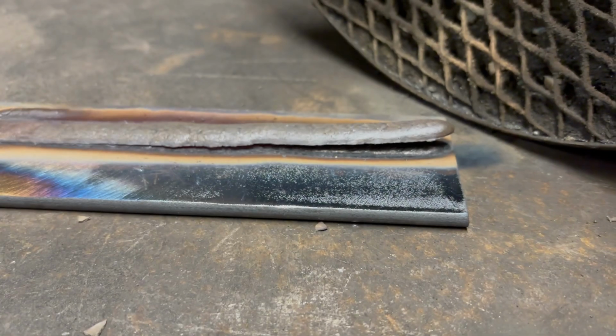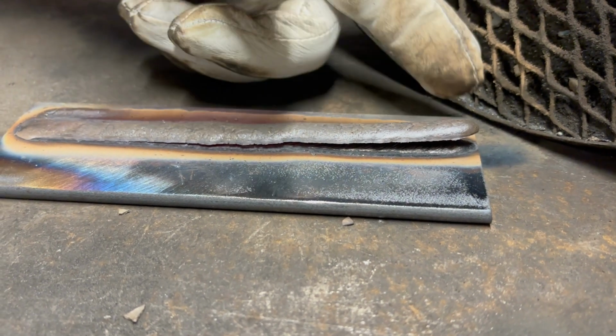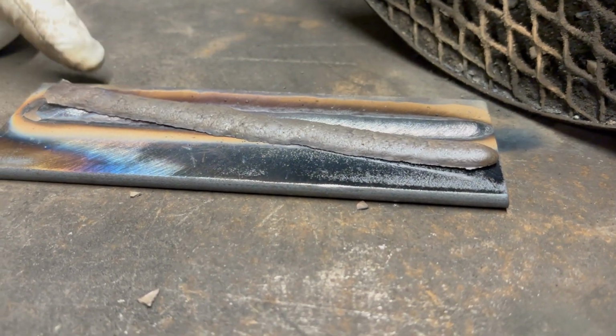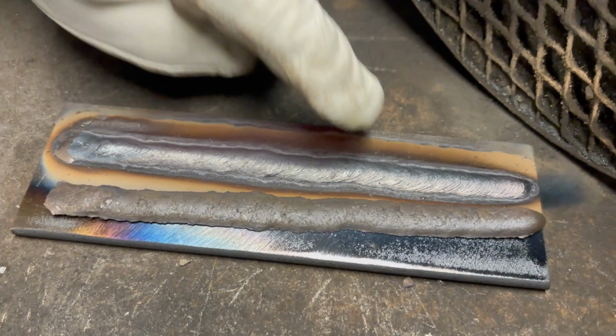Since we're working on thick plate, we'll see how the extra heat affects the weld and what kind of results we get. So we're still maintaining that arc length, keeping a drag angle to keep that flux at the back of the pool, and with the extra amperage we don't have to do any weaving and we're maintaining the width with our travel speed. And now coming to the end of the run, as you can see we have an even better slag peel than on the previous weld. The bead's consistent with nice tight ripples throughout. It's a little wider than the last one because we've pushed more amps into that run.